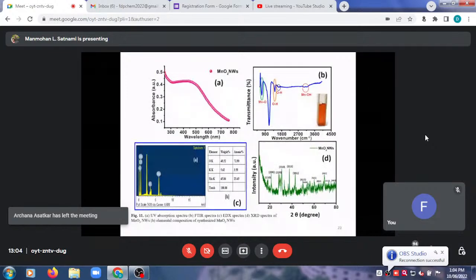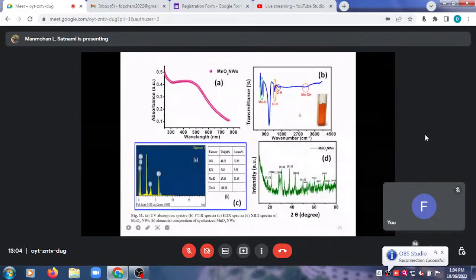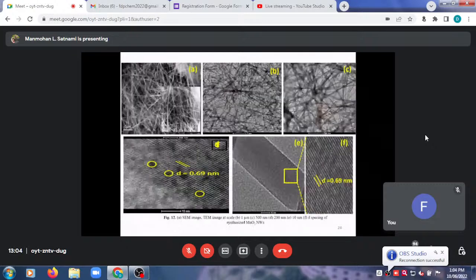So this is again the UV visible spectra of MnO2 nanowire. This is the IR spectra of MnO2 nanowire. This is for the characterization of whether the MnO2 nanowire is prepared or not. This is the EDX spectra. This is XRD, and using all these data, we characterize the MnO2 nanowire prepared.